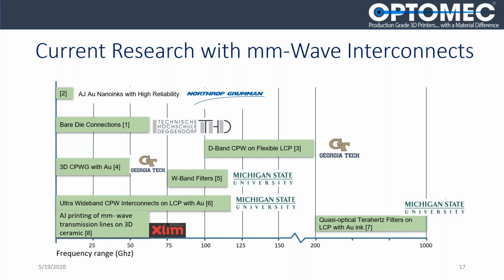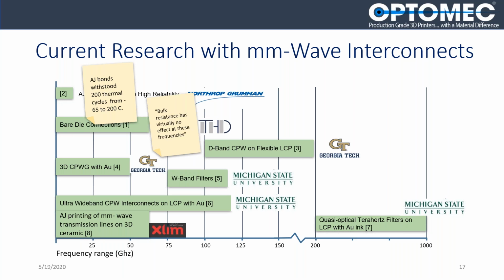But just some key takeaways from these papers that were written by all these different customers. Northrop Grumman did some fairly low frequency work, stating that the printed interconnects will survive 200 thermal cycles from -65 to 200. THD started to push into the millimeter wave space at around 60 gigahertz, noting that the bulk resistance of the wires, because we're printing a nanoparticle wire, which is inherently a little bit higher resistance than a wire bond would be, has virtually zero effect as the frequency starts to climb. That really has to do with the fact that the wires are shorter and the inductance is better than the wire bonds.